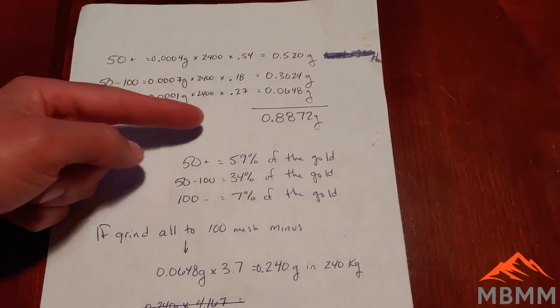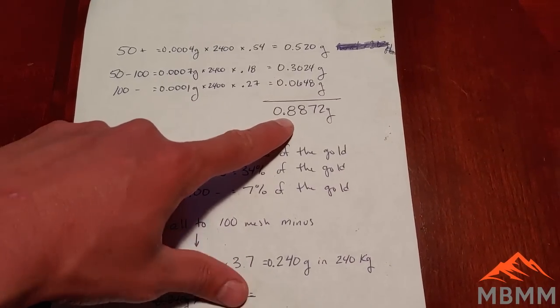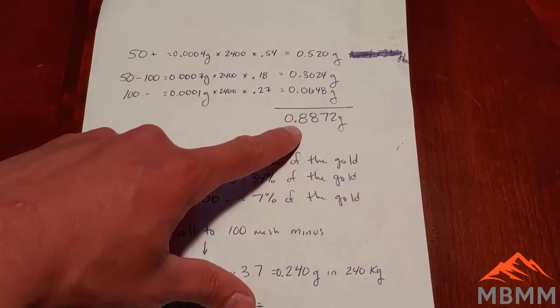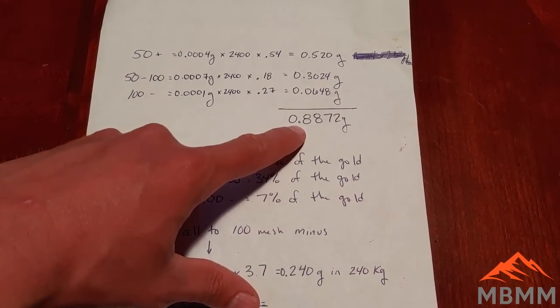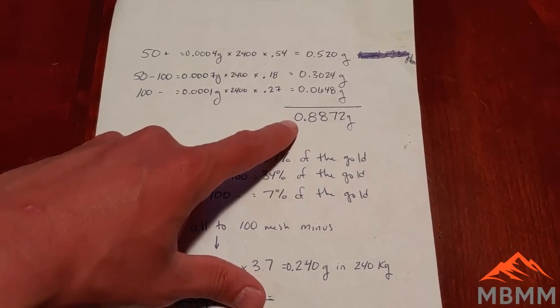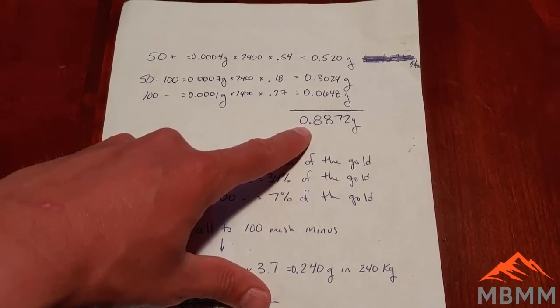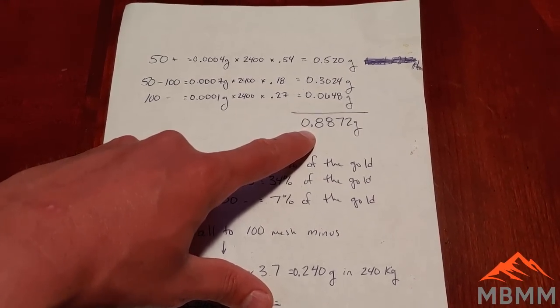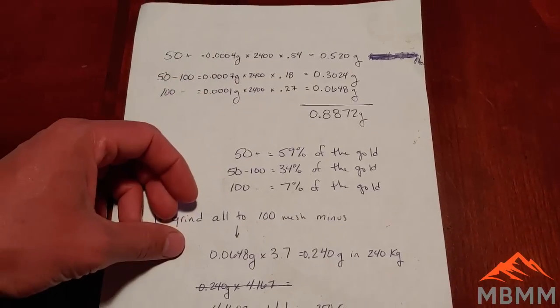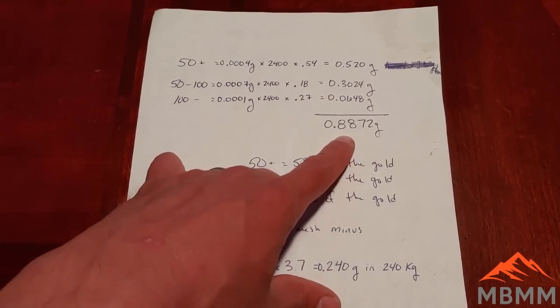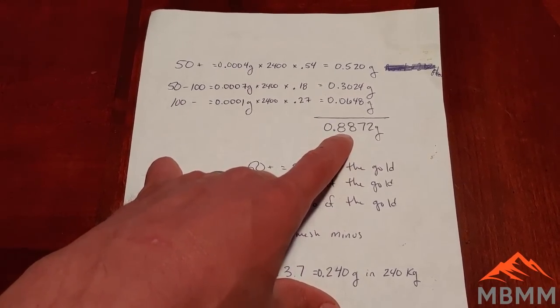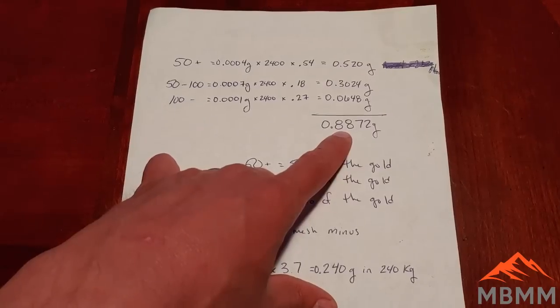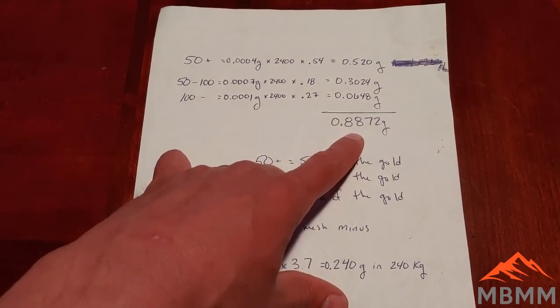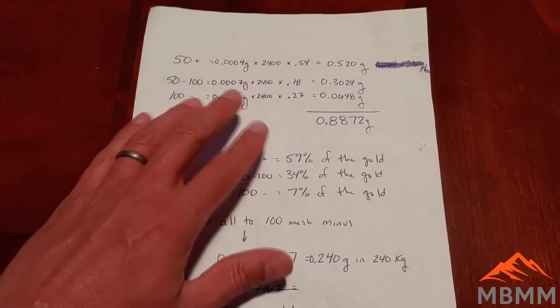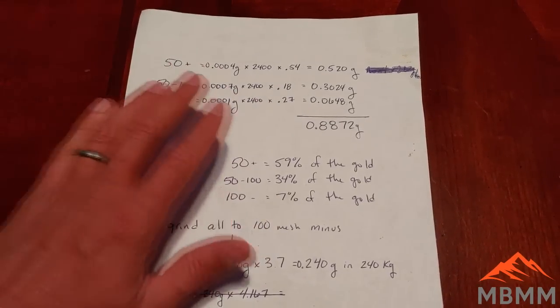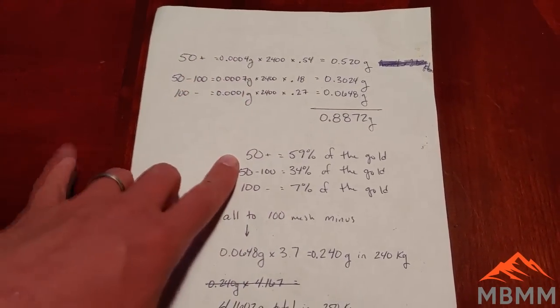And so continuing our math down, here's the amount of gold total in our tailing sample. And you'll notice there's a little bit of a discrepancy here. Our original tailings, we figured there was 1.8 grams, and this is about half of that. So, there's a little bit of discrepancy in the tailings. And surprisingly enough, if you use this amount of gold for the tailings, we actually recovered somewhere closer to 79% recovery as opposed to our 65%. So we're kind of in that range of 65 to 75% recovery probably.